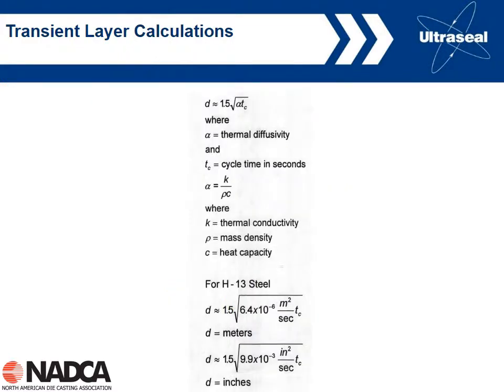So we can do our transient layer calculations. This actually shows how to do it, where the depth is to do with the cycle time and the thermal diffusivity. Thermal diffusivity is defined here in terms of thermal conductivity, the density, and the heat capacity. And for H13 steels, you use these equations here, in terms of meters or inches, depending upon how you want to do the calculation. So you can calculate your transient layer in the die.